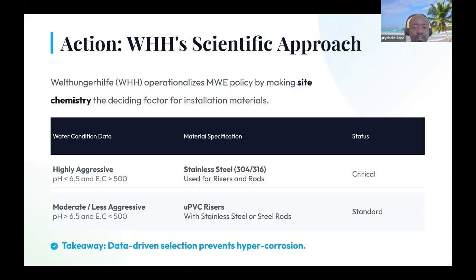When we test the EC and the pH at site, that is where we recommend which materials to install. For aggressive water, where pH is less than 6.5 and electrical conductivity is greater than 500, we strictly go for stainless steel risers and rods, and always recommend 304/316 stainless steel grade. For moderate or less aggressive water, where the pH is greater than 6.5 and the EC is less than 500, we recommend UPVC with stainless steel cupolas and, of course, stainless steel rods. However,